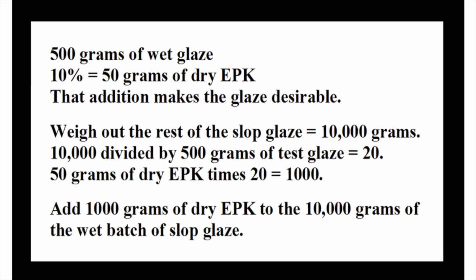So then you have to figure out what to do with the rest of the glaze. I weighed out the rest of the slop glaze—let's just say it weighed out to 10,000 grams. Then I divided the 10,000 grams by 500, which is the weight of the test batch, equals 20.